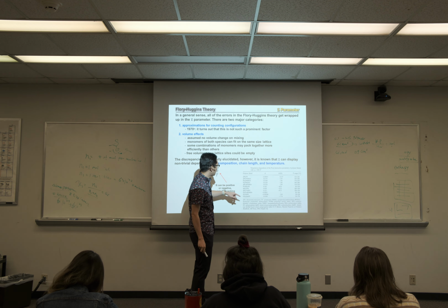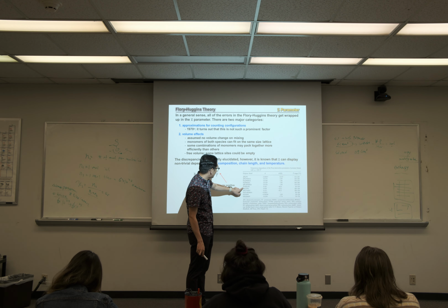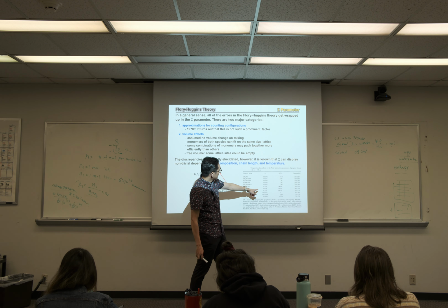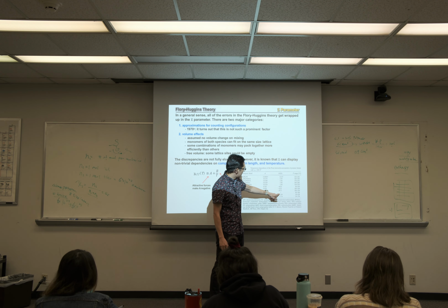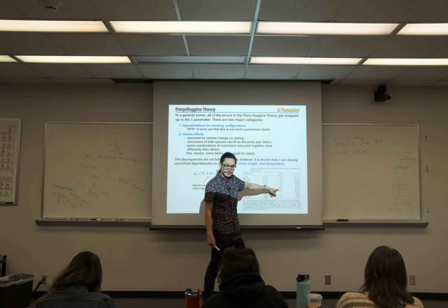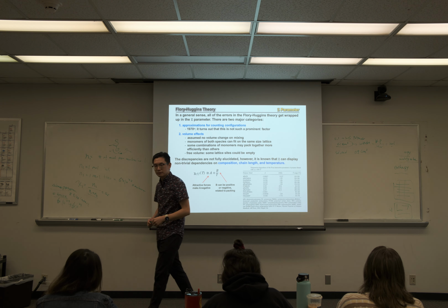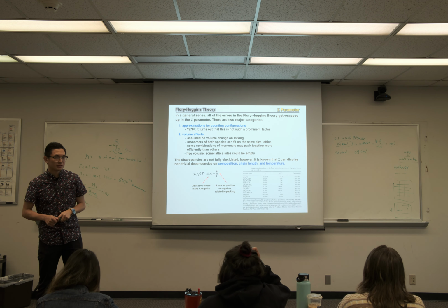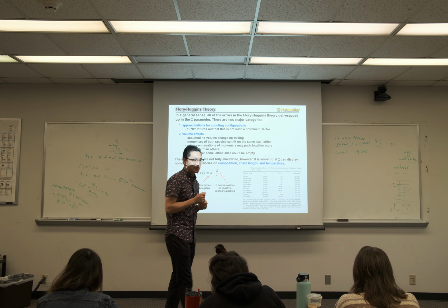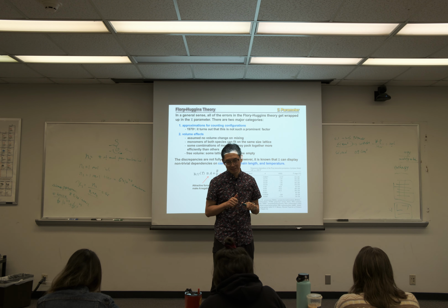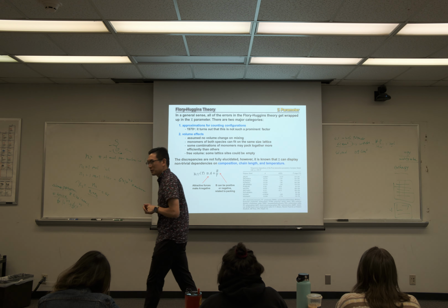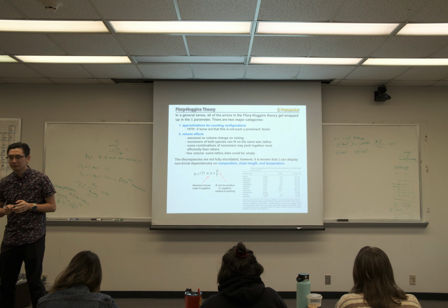So this gives you an example. This lists the Flory-Huggins parameters of some polymers. And you can see some of them have a negative B and some of them have a positive B. That will have an influence. That means when you increase or decrease the temperature, your chi will change, and sometimes it changes quite a lot. So that's why when you're heating or cooling, some systems that were not mixing can be made to mix because you're changing chi. Okay? Because the entropy doesn't change, but your chi is being actively controlled.